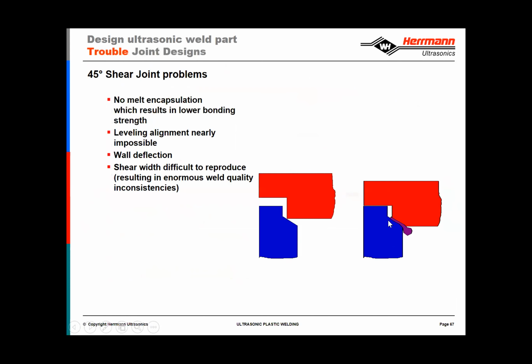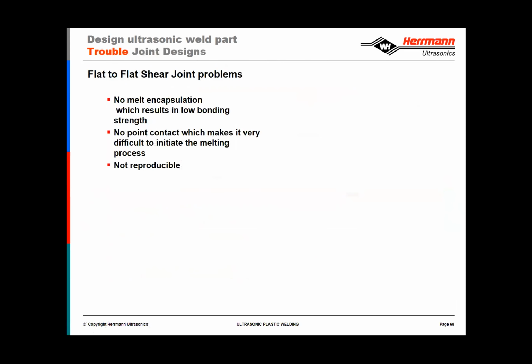No melt encapsulation as well. So very often in a typical shear joint, we do see loose flash being directed to this side of the weld. It's very difficult to get the melt to kind of move up into that area. So again, for those reasons, we typically do not recommend this 45-degree shear.